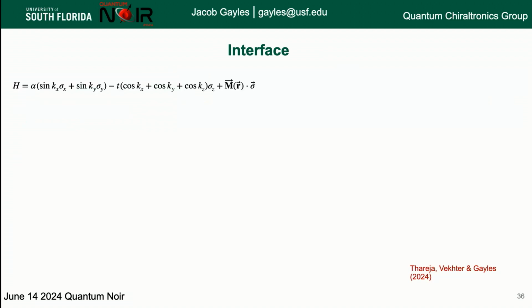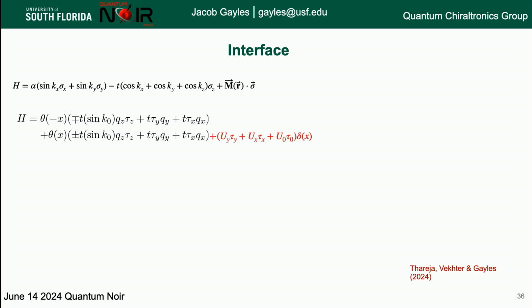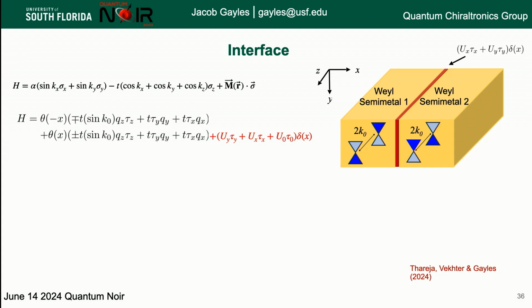And I like to be poetic, so I go back to my previous Hamiltonian. It's the same Hamiltonian, the only thing I'm doing now is I have this step function where on one side of the material I have one chirality for my Weyls, and on the other side a different chirality. And then I can add some potentials at the interface. So this is very far away from the DFT. This is more a linear model, and we're just looking at the scattering theory that goes there.